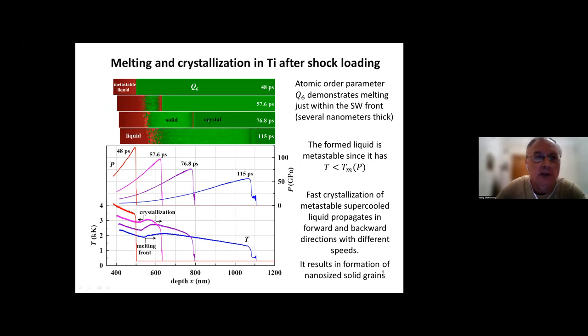Okay, in a little bit more detail about melting. The atomic order parameter illustrates the melting, which happens just within the shock wave front. This front has a very thin thickness, about several nanometers. Actually, it cannot be distinguished here. So you see that the solid immediately melts and some liquid is formed.